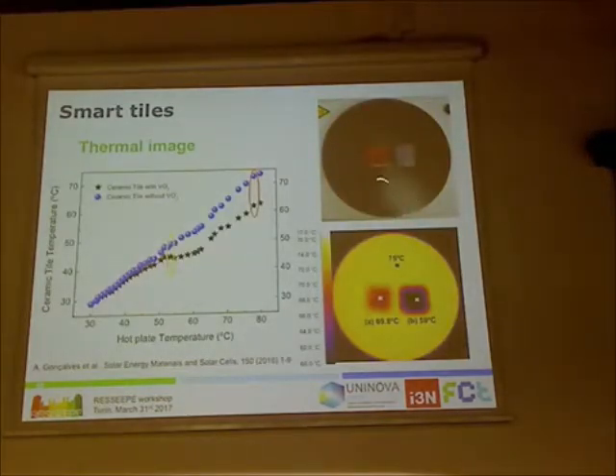Here is a thermal camera image. When you spot the hot plate, the camera measures 75 degrees. Here you have the uncoated tile and the coated tile. If you put the camera on top of the uncoated tile and spot it, you measure around 70 degrees—so the tile is transmitting all the heat from the hot plate. If you put it on top of the coated tile, you measure 59 degrees, meaning it's blocking the heat from coming out, reflecting the infrared radiation back to the opposite side.